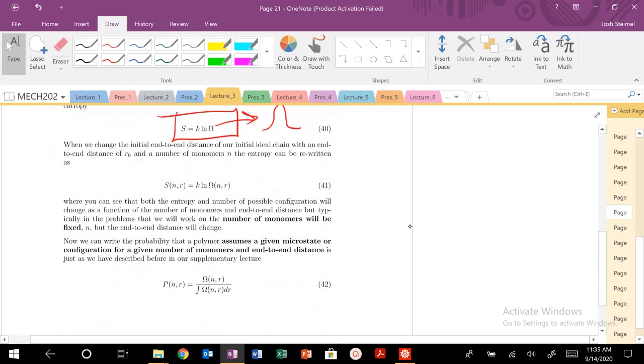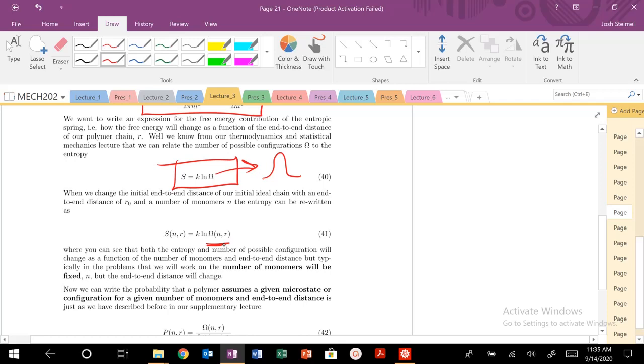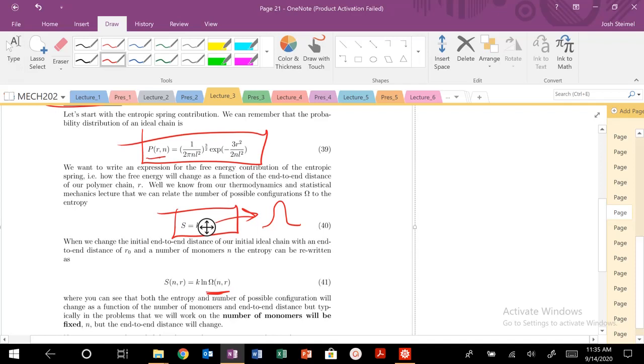The number of microstates is going to change as a function of N, the number of monomer units, and R, the end-to-end distance. We have a fixed N but the end-to-end distance will change. The probability of finding a particular microstate with a particular N and particular R is just that microstate divided by the integral over all microstates — effectively the total number. So the probability of finding a polymer with a particular N and distance R is divided by the total probability of finding all polymers at all configurations, different monomer lengths and distance R.